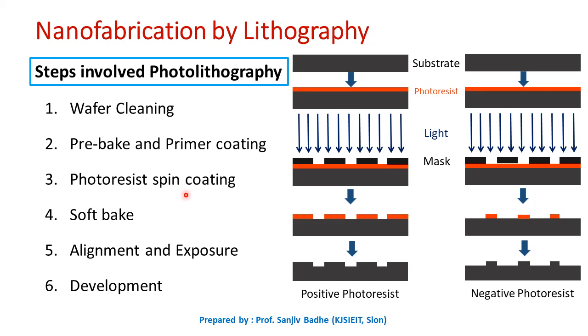After coating the HMDS primer, a spin coat of liquid polymer called photoresist is applied. This photoresist material has high etch resistance and adhesion properties. The thickness of the photoresist coat depends on the rotations per minute and time of spin coating. Rotations per minute and the duration decide the thickness of this photoresist material. Along with the mask, this photoresist material will print the pattern onto the semiconductor wafer surface. After spin coating of photoresist, soft baking is done at around 90 degrees centigrade for 1 minute on the hot plate.